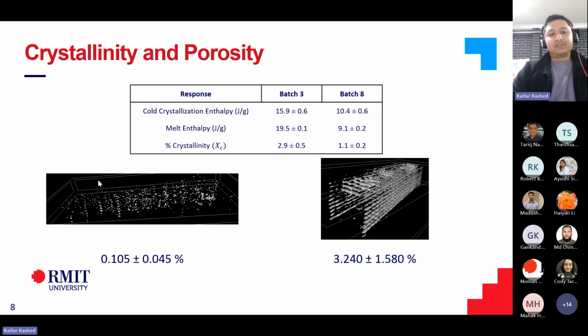In the flat samples, you can see the porosity was around 0.1%, which is significantly low for a custom build printer. But the ones on edge, it was 3.2%, which is significantly higher. So you have a lot more stress concentration points. And since the pores were mostly oval, the representative images you see here are of pores. On the edge sample, you can see the pores are quite large and sort of oval, which is what you don't want, because oval pores can cause more stress concentrations and then cause a premature failure.